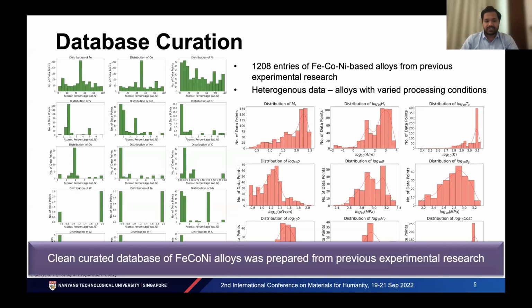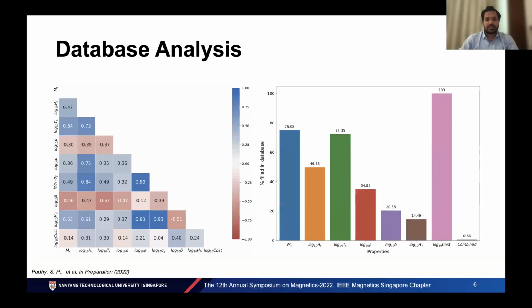So now, after this clean curated database of iron, cobalt, nickel was prepared, a basic data analysis was done. On the left-hand side, we can see the Pearson correlation coefficient chart, which was produced from the data. If I can have your attention to the highlighted box, we can see that hardness has a very strong linear correlation with tensile strength and yield strength. Therefore, hardness was chosen as the main mechanical property for the study.